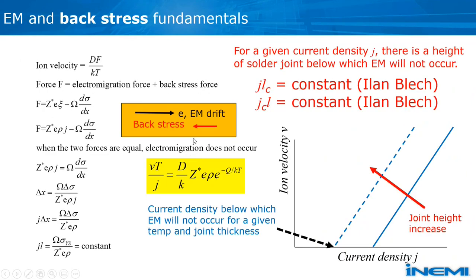So some more background on electromigration. There's a phenomenon called back stress. So if you look at this orange box in the middle of the page, consider that as tin bismuth solder, and electrons are flowing towards the right, shown by this black arrow. So that'll push the bismuth towards the right. So there'll be a stress gradient. There will be very high compressive stress on the right and tensile stress on the left. So that stress gradient will push the atoms back to where they came from. So that's the back stress.